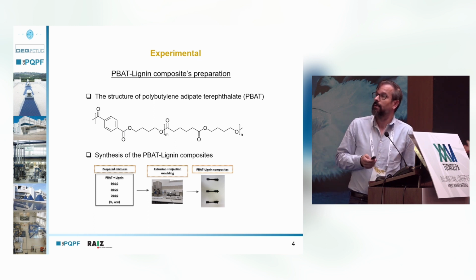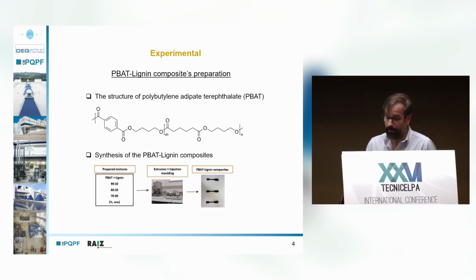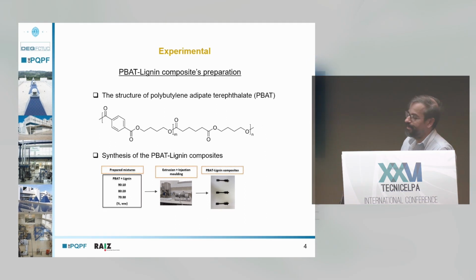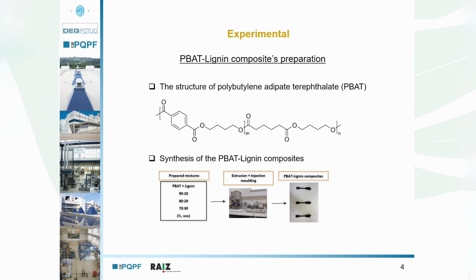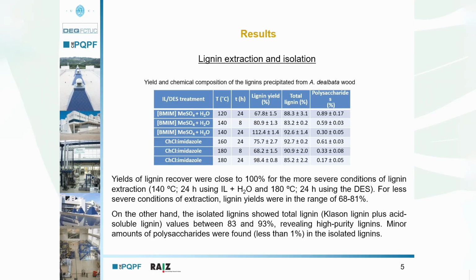These composites of PBAT and lignin were obtained by extrusion plus injection molding. Mixtures were prepared with 10, 20, and 30% of lignin. The composites were shaped in the dog bone format, as you can see in the figure. This format can be obtained by the injection molding we have used in the process. As for the results, I don't have too much time, so I will speak just of a few results and will not extend too much into them.